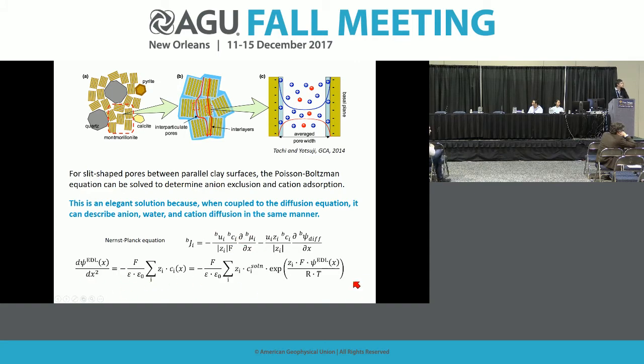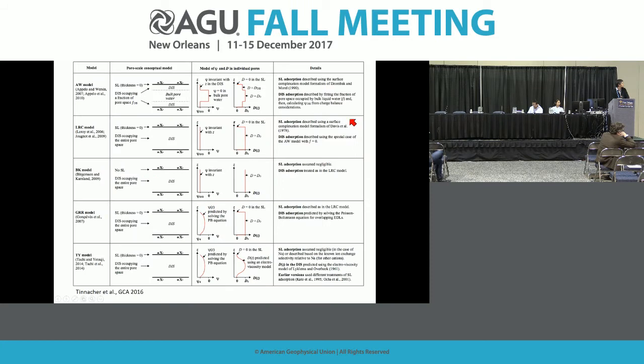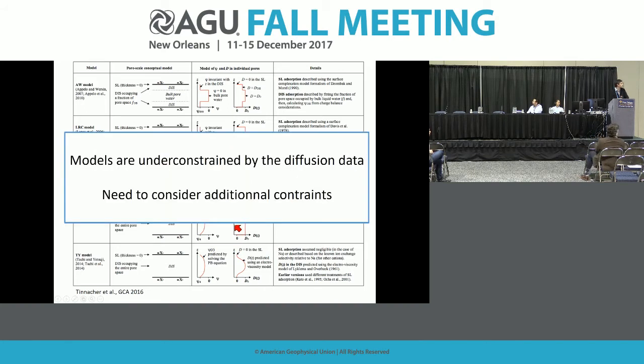And you couple this with the Poisson-Boltzmann equation. So you can find plenty of models in the literature using this kind of approach. All of these models have been successful, but the problem is that the description of what is going on in the porosity is not the same for all of these models. So it means that, in fact, the models are under constrained by the diffusion data. And if we want to understand this, we need to consider additional constraints to these models.